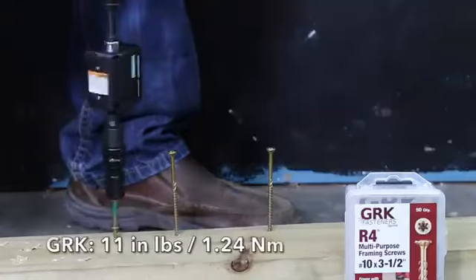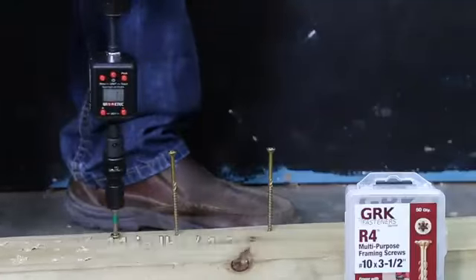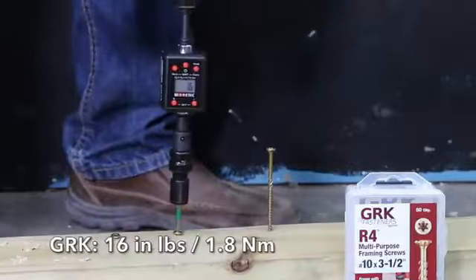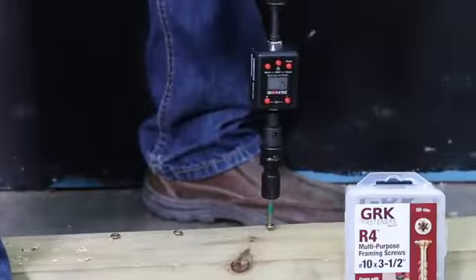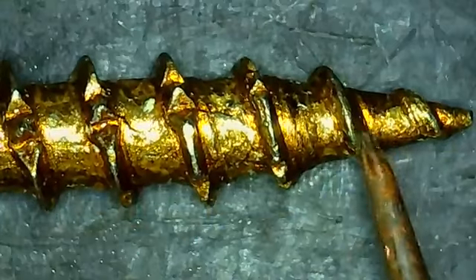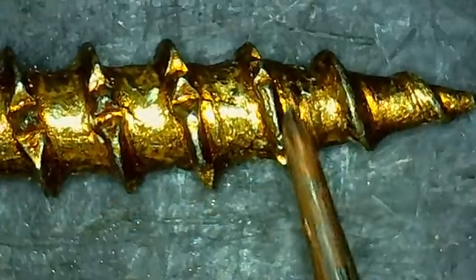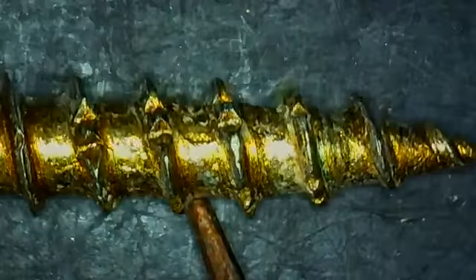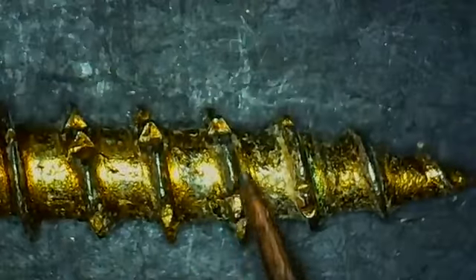11 inch-pounds to drive the first GRK screw. And it took 16 inch-pounds to drive the second GRK. 14 inch-pounds for the third screw for an average of 13.7 inch-pounds. And the GRK held up better than average with a small amount of metal exposure on the outer threads. Even after drilling into the oak, the GRKs held up much better than most of the other brands.